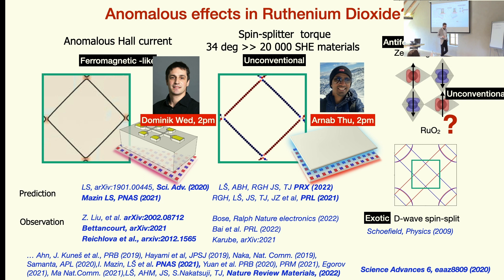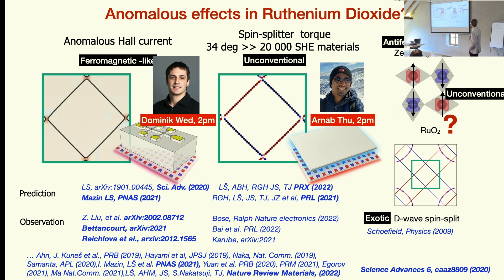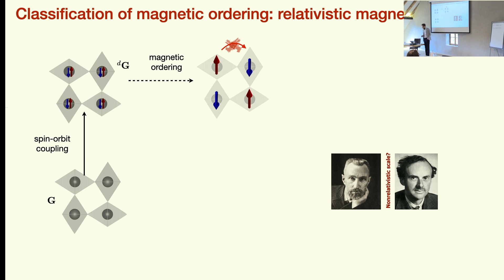I want to conclude the introduction by highlighting the conflict. How should we treat ruthenium dioxide? We have a ferromagnetic-like response, which would suggest it's a ferromagnet, but we also have zero magnetization, which would suggest it's an antiferromagnet. But then we have three exotic properties present in neither ferromagnets nor antiferromagnets: this spin-splitter torque in a very curious geometry, the anisotropic densities in real space, and this exotic D-wave spin-splitting in momentum space that does not depend on relativistic spin-orbit interaction. How shall we understand this from the perspective of symmetries?